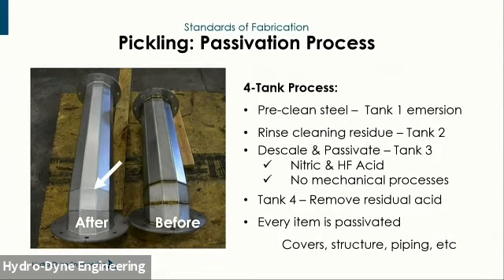Let's talk about that a little bit further. So the pickling and passivation process used by Hydro-Dyne is a 4-tank process. We pre-clean the steel with a tank 1 immersion. We rinse it with a cleaning residue as tank 2. Then we descale and passivate in a 3rd tank, and that's where we have nitric and hydrofluoric acid contact. We don't use mechanical processes there. We don't believe they're as precise and deliver the results. Tank 4, we remove the residual acid, and then we dry every piece.